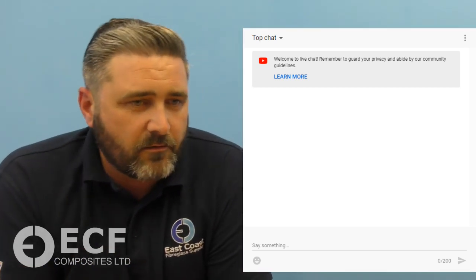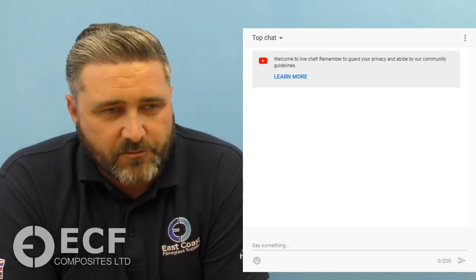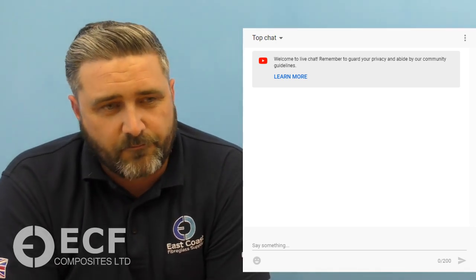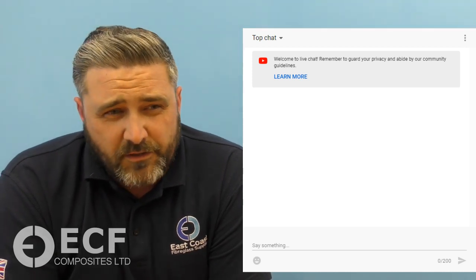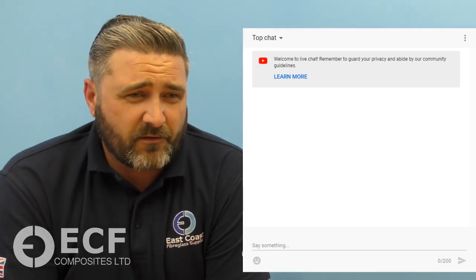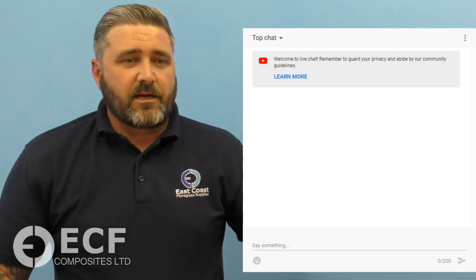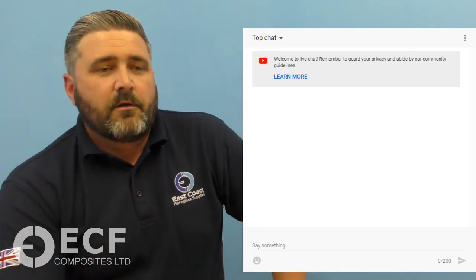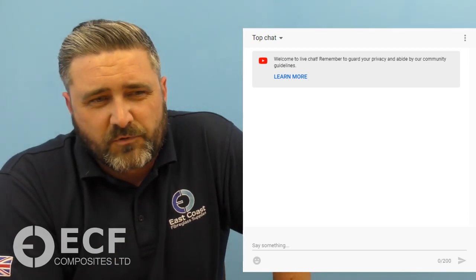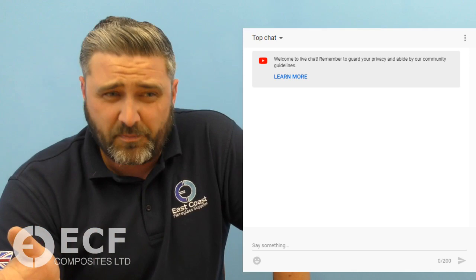So that allows you to use flow coat as a final coat. It's normally used on the inside of boat hulls where a high cosmetic mirror finish isn't important. It's usually more to seal the rough fibres of the chopped strand. But a lot of people like to use it as a paint, which is fine, but I wouldn't really expect a high cosmetic finish. You can buff it up, you can polish it back, but chances are, if you're trying to do something like the cosmetic side of a hull with flow coat, by the time you rub that back to get a good finish on it, you probably end up rubbing back to the hull again. So usually it's a good idea just to assess the situation. It may be better just to paint the boat rather than trying to re-gel or flow coat it.